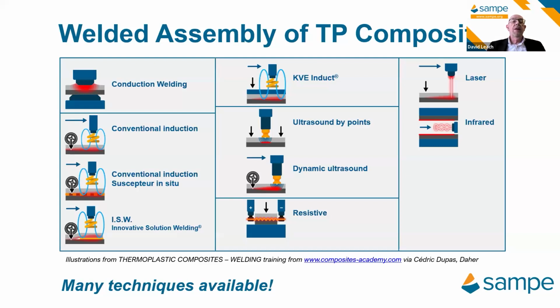Then there are a range of different induction welding methods. With carbon fiber, you can actually use the induction process to create electric current in the carbon fiber, and so use the carbon fiber itself as the medium to heat up during induction. You can use a susceptor, usually a metal mesh, in order to induce the current in the weld area.